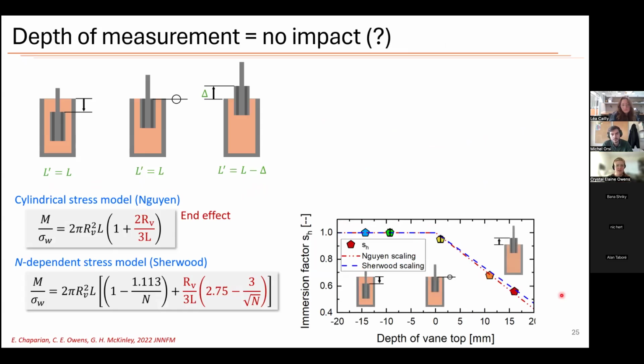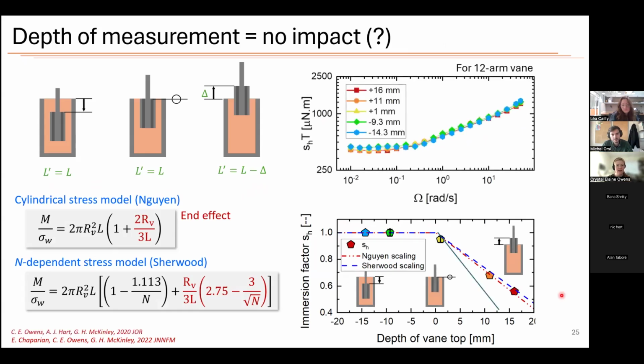And it turns out that this actually was able to, without any modification, collapse all of our data onto itself. And so this is a very interesting finding, because it means that we're measuring the same data no matter how deep the vane is in the material.